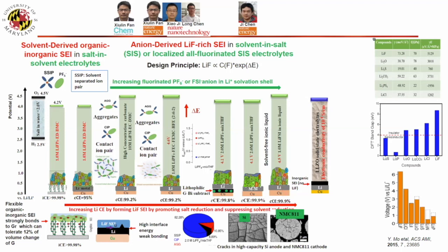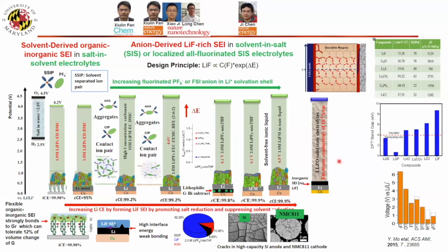Another way to totally get rid of the solvent is solid-state electrolytes. With solid state, we can consider there is no solvent. It should be perfect. But when we use sulfide, they bring additional challenges. They have electronic conductivity, which in liquid electrolytes they never have. Second, in liquid electrolyte we can easily adjust the composition to form lithium fluoride, but in sulfide you never form lithium fluoride. So those two challenges make the Coulombic efficiency even lower than liquid.